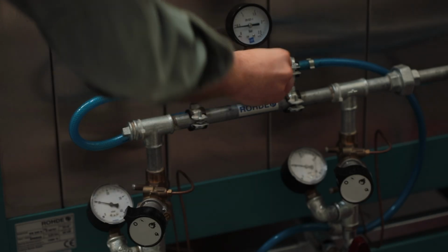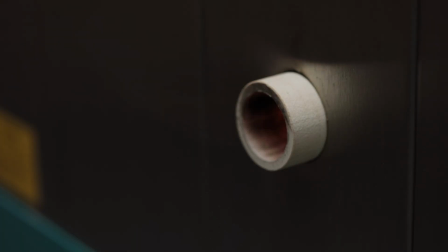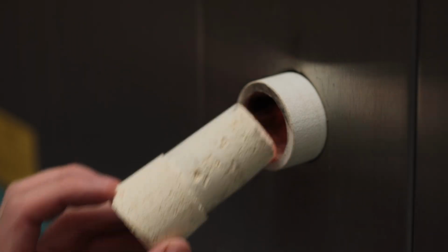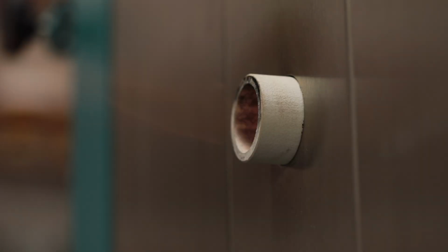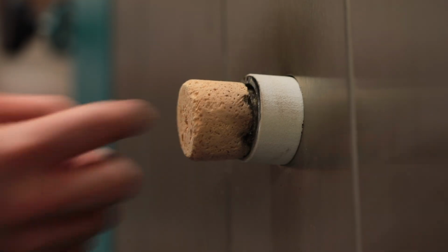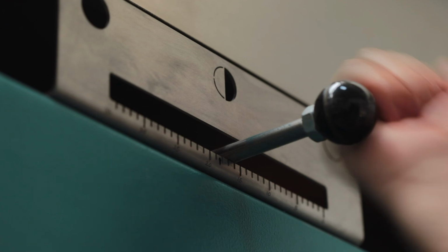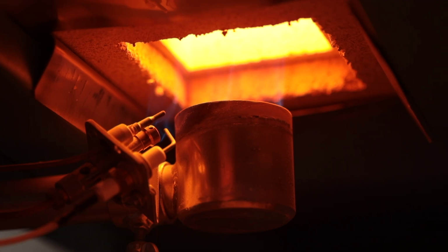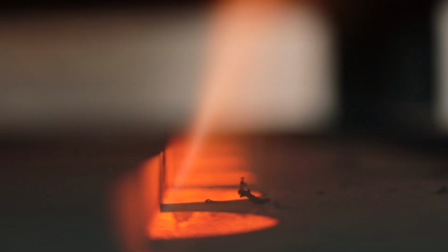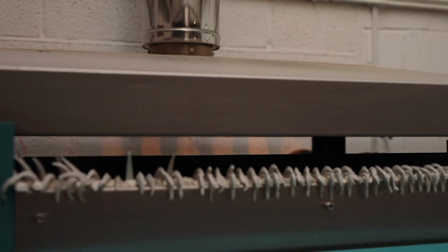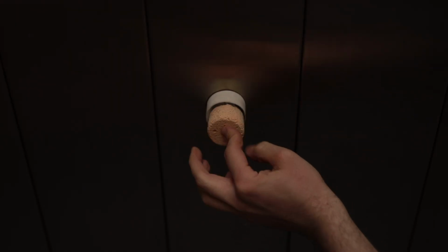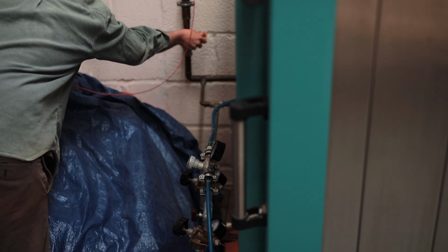I do this by dramatically increasing the gas and air pressure and by sliding a damper over the flue of the kiln. This limits how quickly the exhaust can escape, and simply put, there ends up being too much fuel in the chamber with an insufficient amount of oxygen present for it to burn properly. As a result, the atmosphere inside begins to seek oxygen from inside the clay and glazes themselves, stripping it away, the oxygen bubbling out, changing the iron molecules themselves, and creating colours and textures that you can't really achieve in quite the same way with an electric kiln.